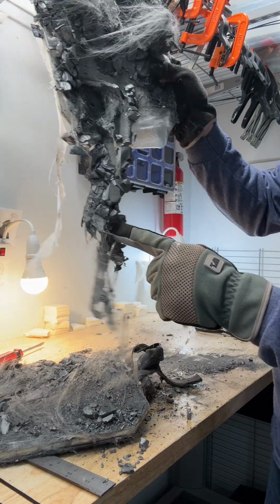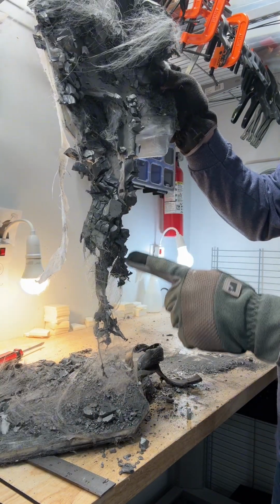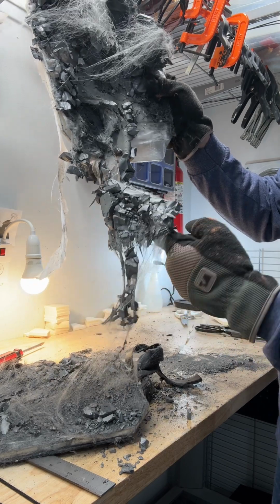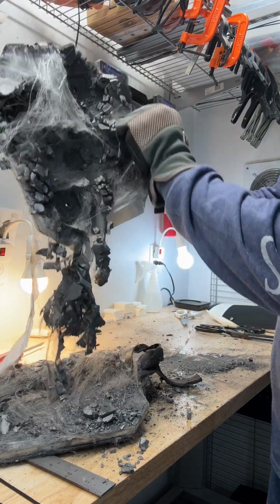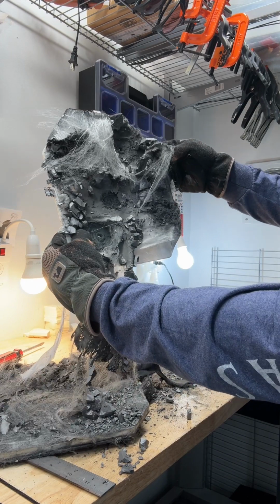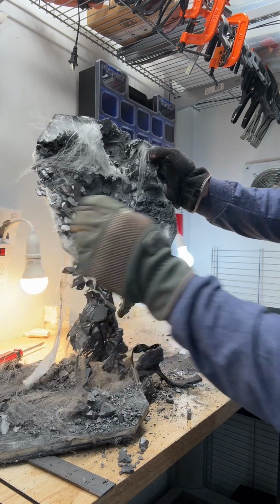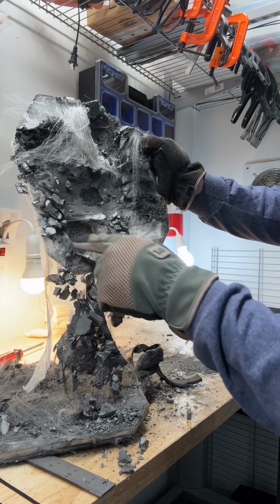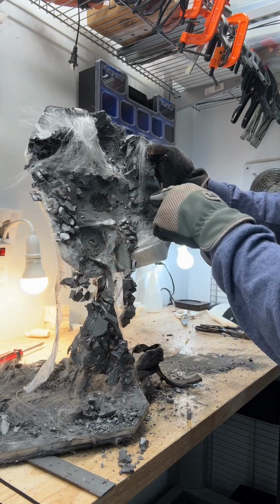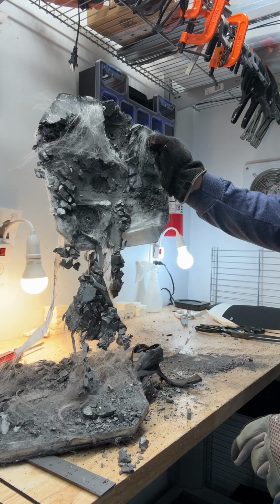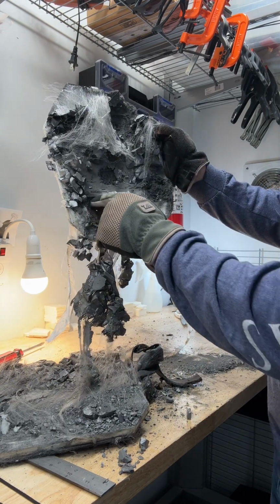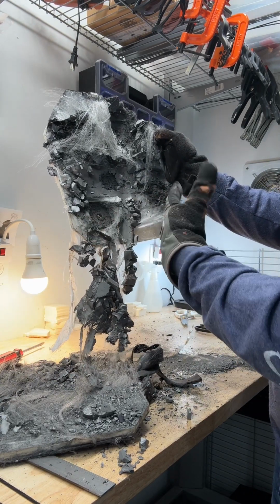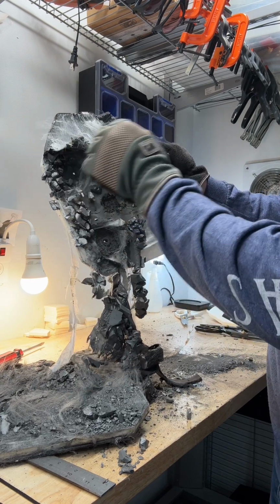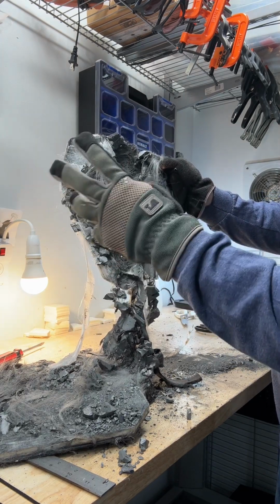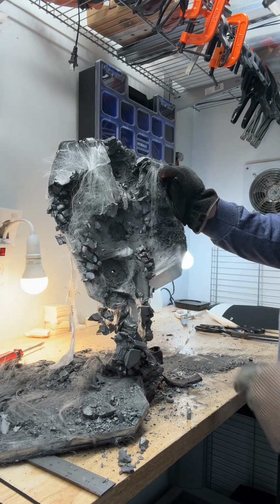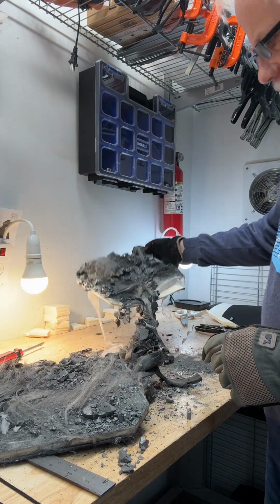You can see how good the adhesion to the ceramic is here. You can see light, you can see daylight through there. That means that crack arresting layer works. And you see the limited amount of area right here that the strike face was allowed to get damaged by that ballistic energy. So it trapped that energy and dispersed it back through the adhesive layer. And this type of fiber and the elongation of the material itself allowed that energy to be absorbed.